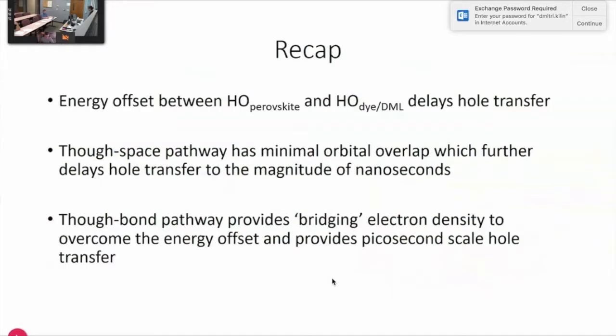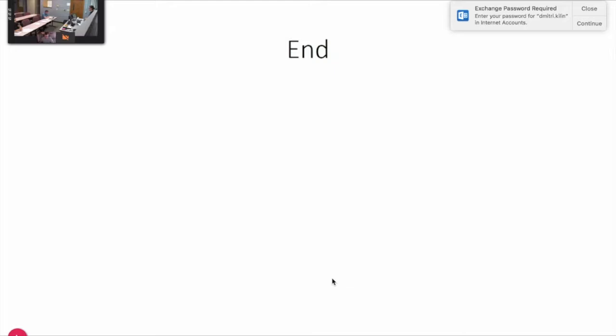So just to recap what has been covered in this presentation. The two big things to look for: the large energy offset between the perovskite and the dye is going to slow down the hole transfer process, strictly due to the energy gap between them. And the through space pathway will have minimal overlap, which corresponds to long hole transfer rates, while the through bond pathway provides bridging, which will correspond to very fast picosecond transfers. And that would be the presentation.